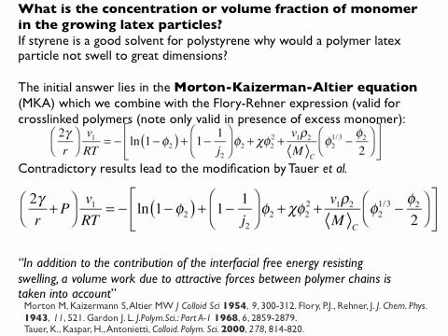And it's multiplied by the density of the polymer, and then divided by the molecular weight between cross-linking points. So if there are no cross-linking points, that term basically goes to infinity, and it just completely disappears.